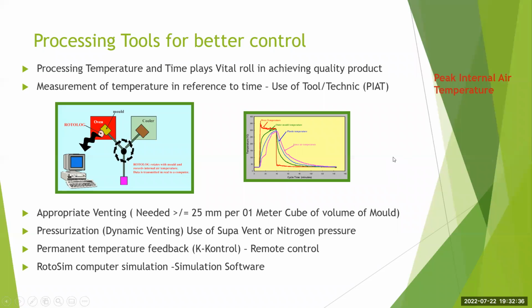Another very important parameter is controlling the process parameters. Now, if you see the photograph, you have to control the processing happening in the mold. Unfortunately, roto molding is an energy consuming technology. The oven is heated, then the oven heats the mold surface, then the mold surface heats the material. So it's basically an indirect heating mechanism, and a lot of heat energy is utilized to manufacture a product. So it is very important how you control the temperature, because you also need a good product, good melt, without decomposing the polymer.